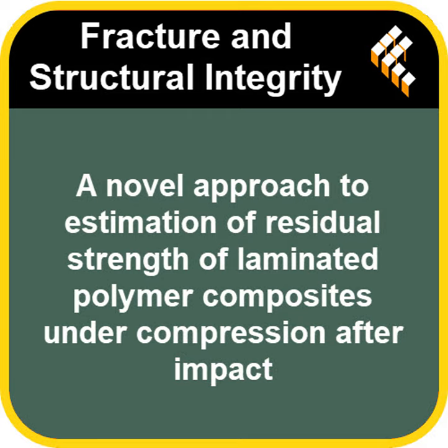It highlights again that because the damage mechanisms are different with those angled fibers, penetrating the material doesn't immediately equate to reaching its absolute lowest strength level. There's still some residual capacity being utilized differently. So essentially, this approach gives engineers a really robust, mathematically grounded way to understand exactly how impacts degrade these critical materials, and maybe more importantly, to pinpoint those critical points of no return, those thresholds. That seems like an incredibly powerful tool for design and safety assessment.